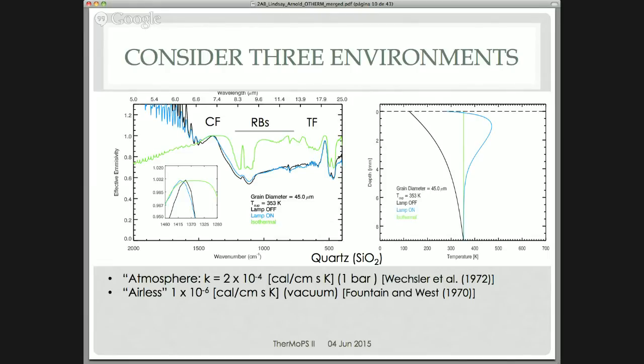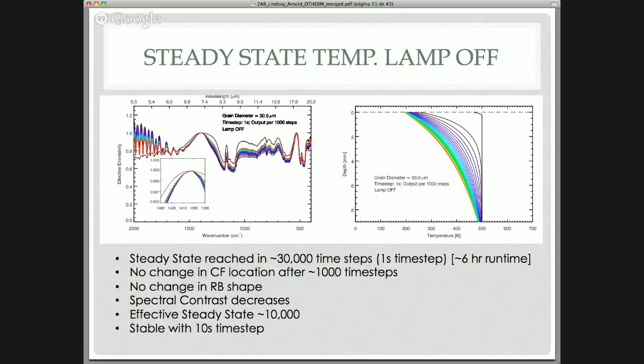One of the more interesting ways to start investigating the temperature gradient is to let the model run all the way to steady state. This will give us some ideas of how long we actually have to integrate for, and whether we have to go all the way to steady state. With this very dense plot, we start with an initial isothermal temperature gradient, then allow time to integrate forward, using 1 second time steps. Every 1,000 time steps, I'm outputting the temperature gradient, and I let it evolve all the way until it reaches steady state, so the exit criterion kicks in.